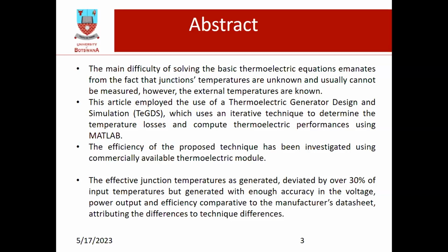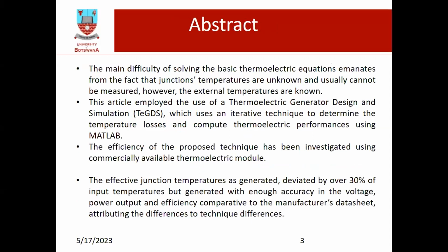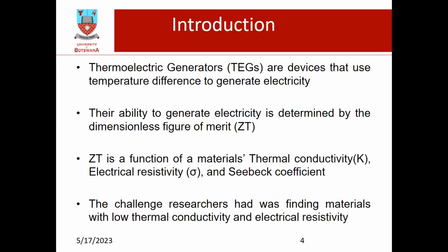The efficiency of this technique was validated using a commercially available thermoelectric module, and the effective junction temperatures generated deviated by over 30% from the input temperatures, of which the difference was attributed to the difference in techniques applied by the manufacturer and by our team.